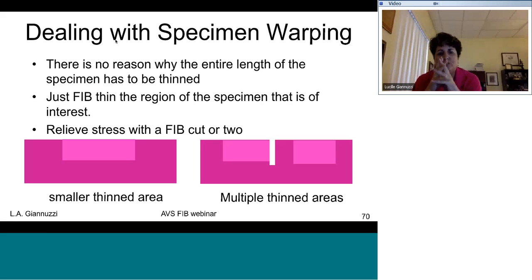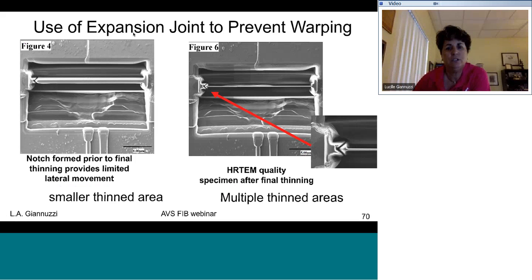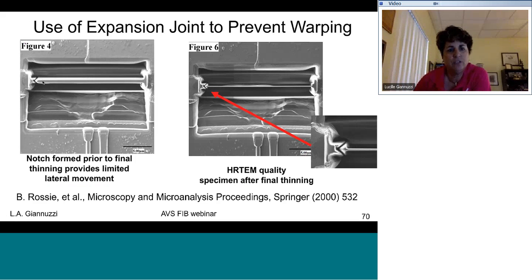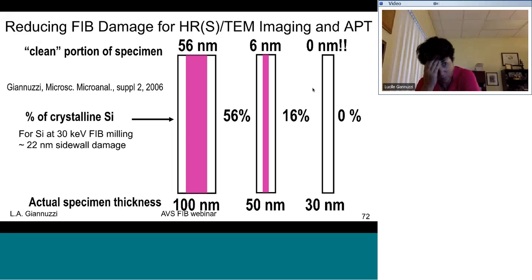A couple of things you can do is you can relieve the stress with a FIB cutter too. You can just make smaller windows. You don't have to thin as big as material. Here's an example using ex situ lift out by just FIB milling this little arrowhead. And this little arrowhead allows the sample to move slightly but still staying sort of upright, if you will. And then the sample is just cut free over here and then manipulated to ex situ lift out. Okay, now let's just finish up by talking about low energy polishing.